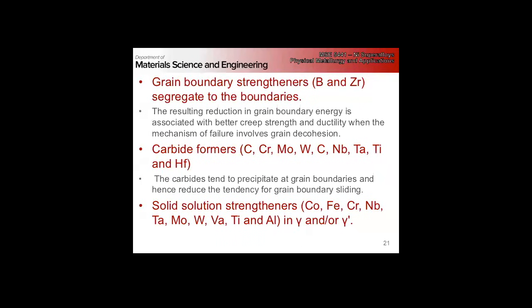Carbide formers - here's a list of carbide formers - these carbides will tend to precipitate at the grain boundaries and reduce the tendency for grain boundary sliding at higher temperatures, which is critical for creep. And then we have our solid solution strengtheners, which give us additional strength in both our gamma and gamma prime phase.